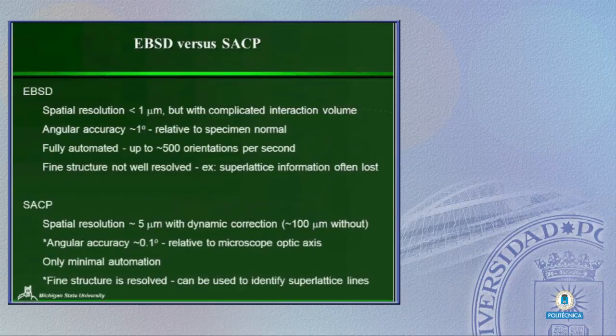Okay. So to compare those a little bit more, EBSD has spatial resolution certainly less than 1 micron. Some people will say tens of nanometers. It really all depends on how you're defining your backscattered electron interaction volume and how that is as a function of direction in your tilted sample. It has a fairly complex interaction volume. The angular accuracy in general is not all that good.